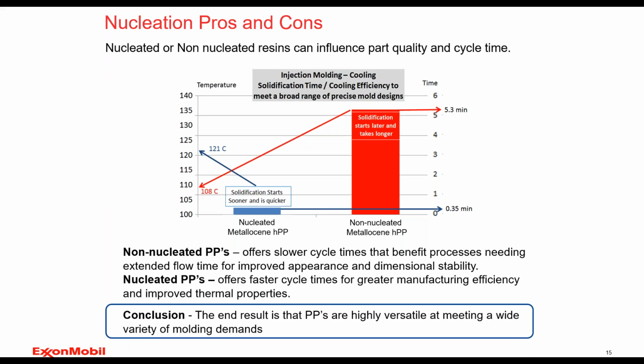Think about this graph from a molten standpoint or from the resin's point of view. The resin is molten in the barrel of the machine. It's being injected into the cavity. At that molten state, the resin is about 230 degrees C or 450 degrees F. And as soon as it's injected and hits the sidewalls of the mold, it begins to cool. And once the cavity is pressurized, the heat transfer out of that resin is very, very rapid. And that's why this chart is shown in terms of the T1 half-time or isotherm representation of these materials. So what happens is that resin is cooling rapidly.